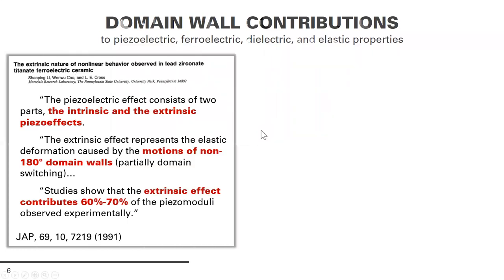One of my favorite papers on this was in 1991 by Eric Cross and colleagues, where they said the piezoelectric effect consists of two parts, the intrinsic and the extrinsic piezo effects. The extrinsic effect represents the elastic deformation caused by the motions of non-180 degree domain walls. And studies show that the extrinsic effect contributes 60 to 70% of the piezo moduli observed experimentally.